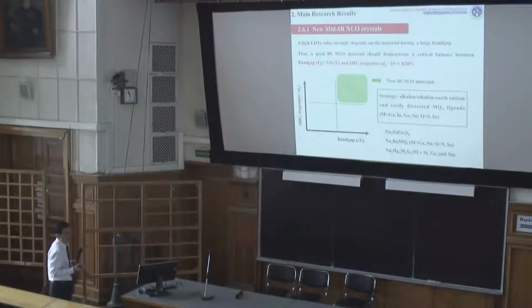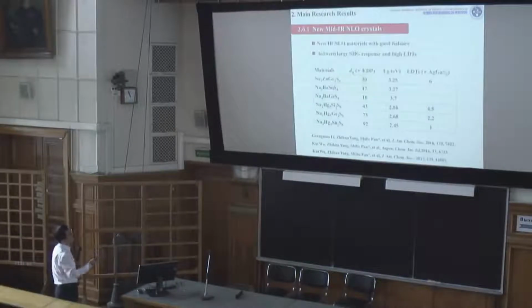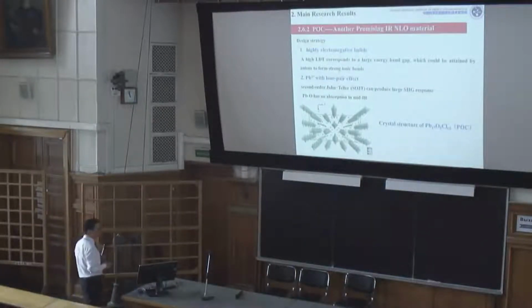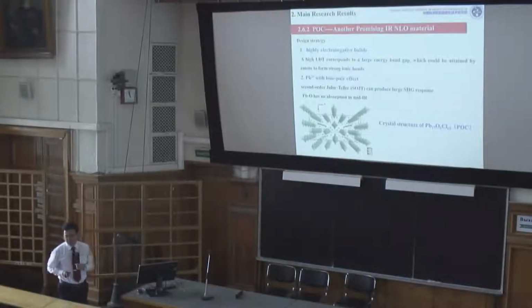In fact, why is it difficult to search for infrared nonlinear materials? From our systematic research, we found that if we want to get an excellent nonlinear material, the material should have a critical balance between band gap, in general larger than 3, and SHG, in general larger than 10 times that of KDP. And we found several materials. These materials can balance between band gap and SHG. It means these materials have excellent properties. And also, we want to search for new IR materials. These materials can grow in atmosphere and with large laser damage threshold.